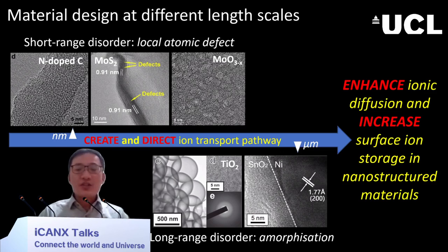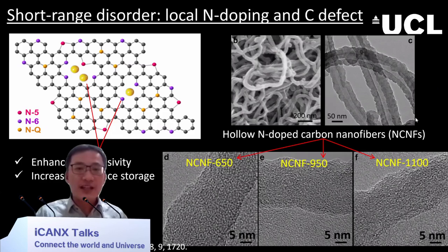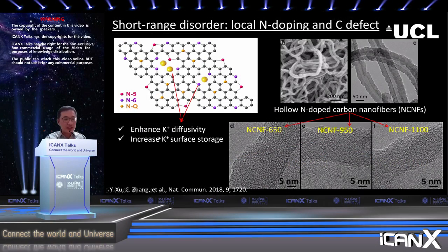So due to the time limitation, I won't be able to explain all the work in this slide. I will just use a couple of examples to showcase our design strategy. I would like to start from the carbon materials because it's a very sustainable material. It's low cost and it has the ability to be scaled up. So what we have done is to use nitrogen doping in the carbon material to create the carbon defects. These defects could not only enhance the diffusivity of potassium ions, but also increase the surface storage of potassium ions.